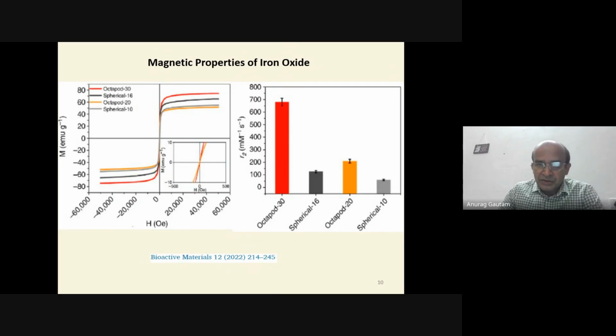So this is for the octopod, 30 nanometer size. I said 700 per millimolar per second. If it is a spherical particle of 16 nanometer size, they have a different relaxivity, around 100. For iron oxide, this varies for different elements, different oxides, different shapes. If it is an octopod of 20 nanometer, they have 200 per millimolar per second relaxivity. So that's how it is.